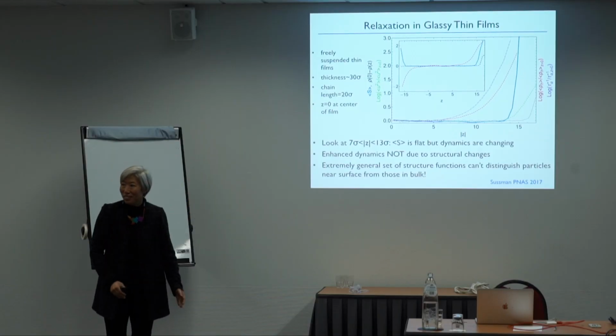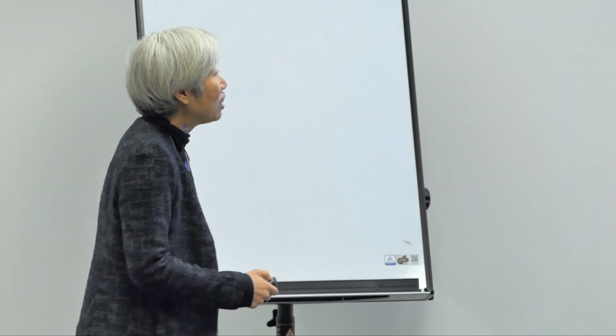In fact, for the structure, this was a huge shock. I can use just an extremely general set of structure functions and ask, can I tell which particles are at the surface and which ones are in the bulk of the film? I'm just going to train on that, not worry about dynamics. Can I just tell where I am in the film? No. If you just look at structure, you cannot tell where you are in the film. It's just flat. So structure is the same until you get really close to the edge of the film.